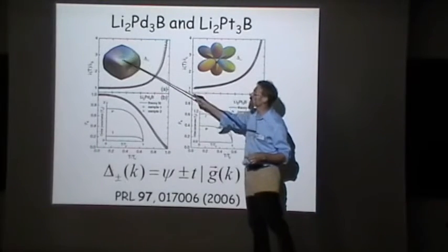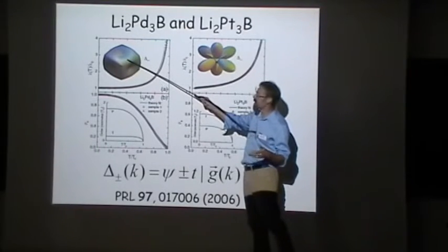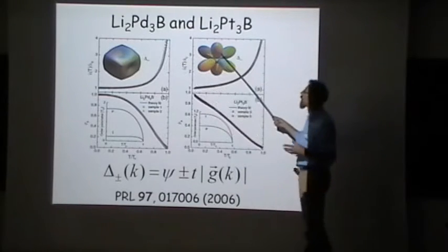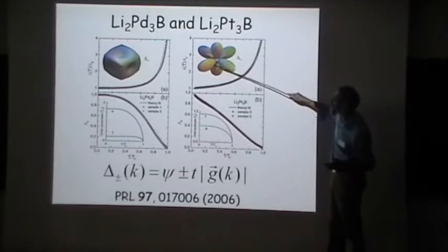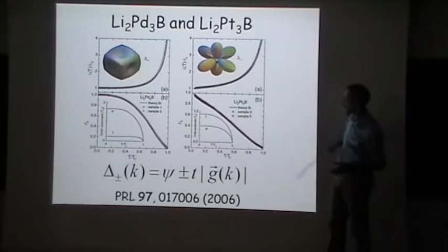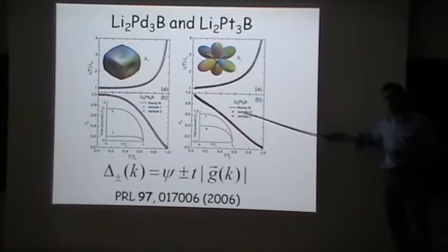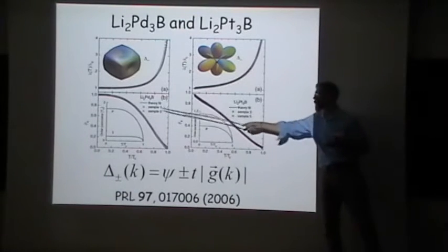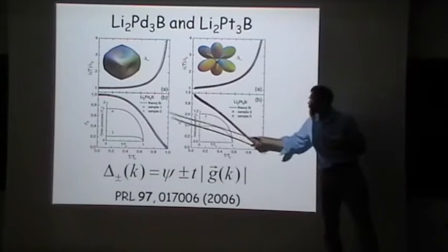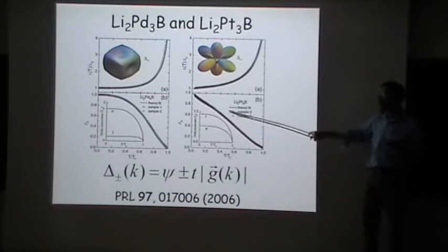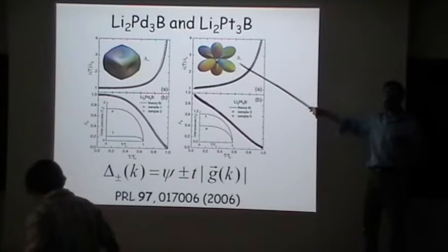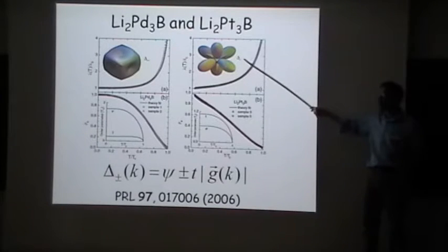Here's a small spin triplet component; you can, in essence, get an anisotropic gap. Here's a much larger spin triplet component, and you get these little line nodes in this s-wave superconductor. Now, this is really the only evidence for this picture, and again, this picture is not so strongly supported by other experiments. The appearance of nodes is not strongly disputed, but the origin of the nodes is not confirmed. There are many other possible explanations for that.